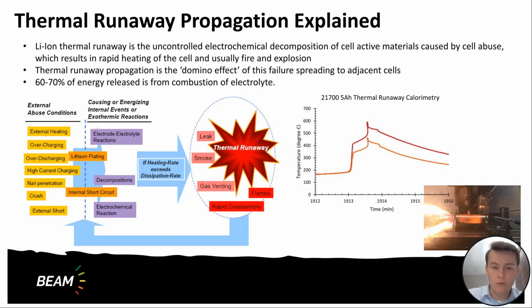I think one key message here is that the energy that releases from the cell during a thermal runaway is 60 to 70% caused by that combustion of the electrolyte.